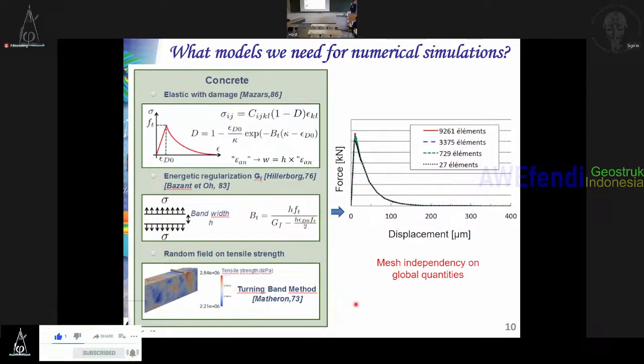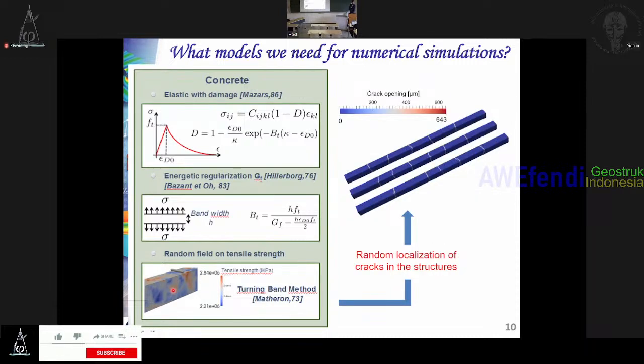And since cracking occurs where you have some flaws, you need to perform several finite element calculations. Dirk was talking about Monte Carlo. We will not do 1 million, 1,000 numerical simulations, just a few simulations. But since the material is heterogeneous, we use techniques to have a random field inside the concrete. It can be used to represent flaws, to represent aggregates, etc. It's a technique that is very easy to use, because measuring the aggregates and the porosity is not possible. And you can perform numerical simulations afterwards.